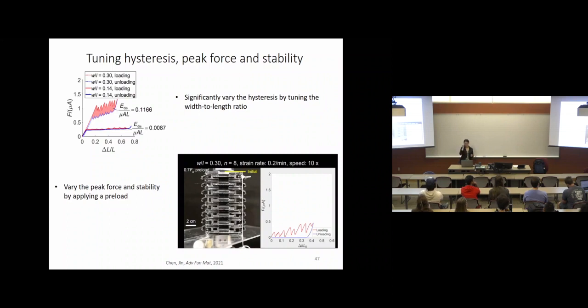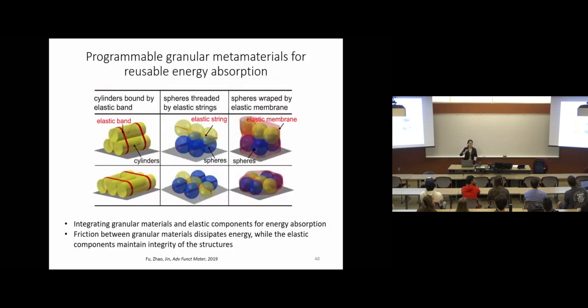Moreover, this is an architected material, or mechanical matter material, so its properties are governed by geometry. I can tune the aspect ratio to significantly reduce the energy dissipation. If I apply a preload at the bottom, I can also shift the peak force, and in this case I also change its stability. When I load it, different layers buckle, but when I unload it, it actually becomes bistable. It can lock in the deformed state even when you remove the load. So this is one idea: making use of snapping-back instability for energy dissipation.